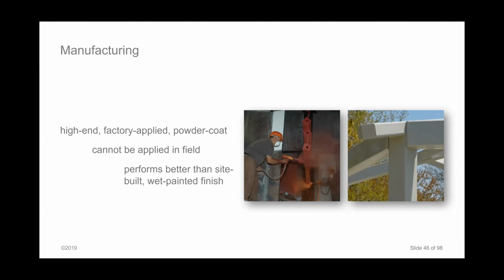Manufacturers may provide corrosion protection through the use of primers applied to clean steel. Some use zinc-rich primers and some use an epoxy e-coat primer, the latter of which is similar to what auto manufacturers use on vehicles. The final color, in the form of a TGIC (triglycidyl isocyanurate) curing agent polyester powder coating, is applied over the primer. The coating is electrostatically applied and then cured onto the steel. A 4 to 6 mils powder coating is typical, with some manufacturers providing a coating thickness of 8 to 12 mils. Mil thickness is a common measurement in manufacturing. A mil is a unit of thickness equal to 1/1000th of an inch.